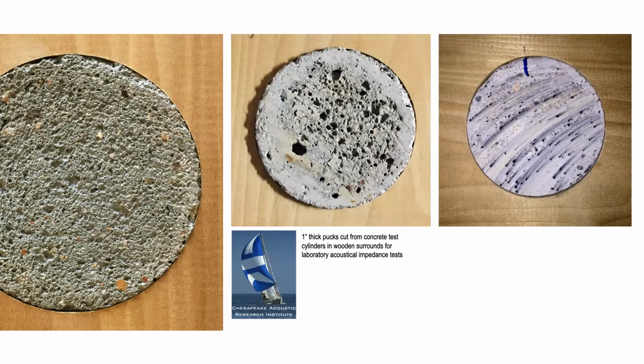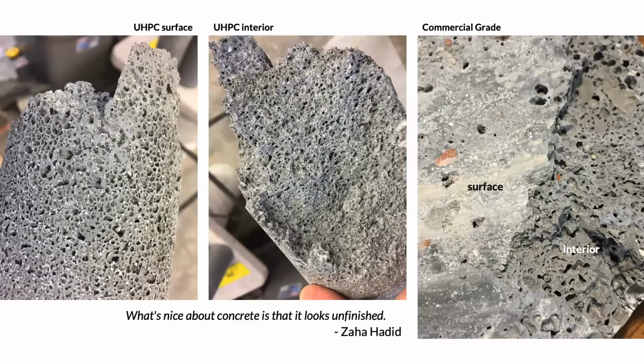The cylinders were cut into 1-inch pucks and combined with other samples from industry partners for separate ISO impedance tube acoustic tests to determine NRC values. The results showed weight differences along with variations in porosity, shape, and size. The team continued with concrete mix designs of various percentages of aluminum powder and both white and gray type 1-2 cement due to particle size affecting the reaction time and subsequent surface and interior porosity. The aluminum reacts with the cement to create hydrogen gas bubbles during hydration. Sound is absorbed through friction as it navigates through the pores.